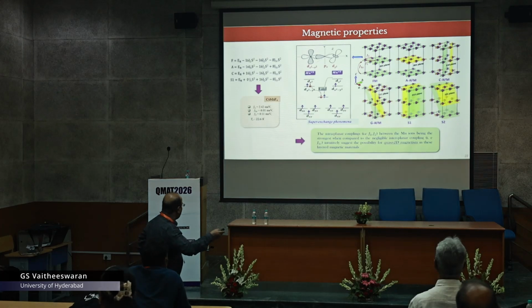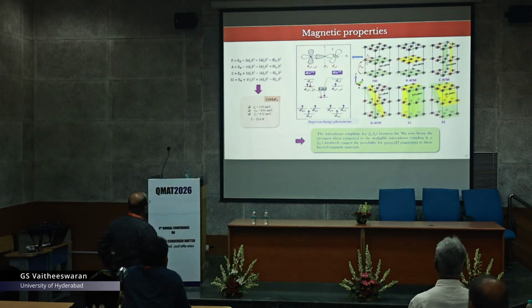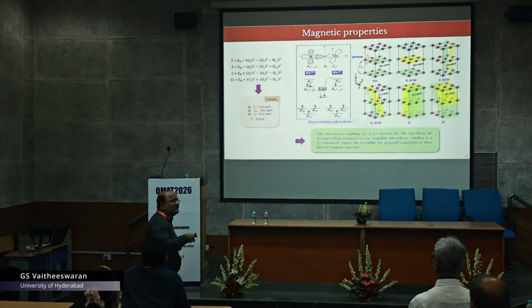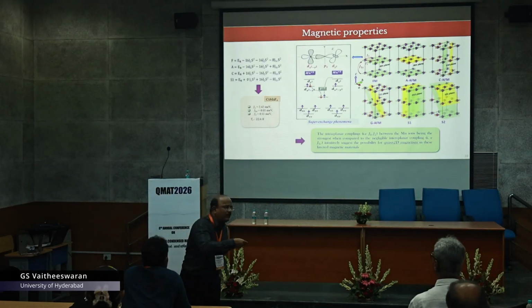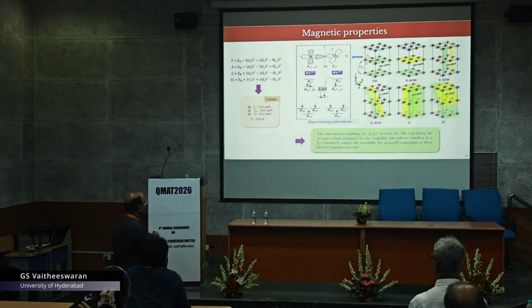temperature, which is not so great because the Heisenberg model is well known to overshoot, and then we got around 22.2 Kelvin, which confirms it's a weak ferromagnet. The Curie temperature is not very strong here, so that is our conclusion.